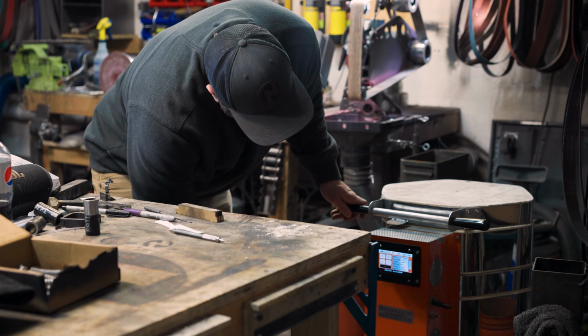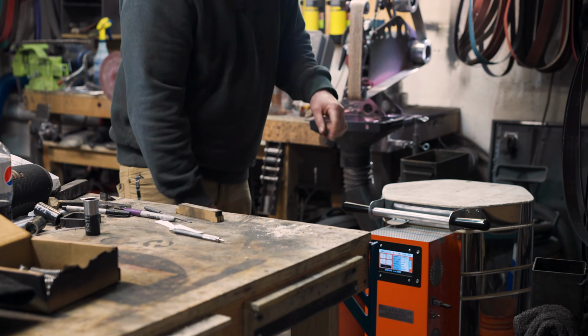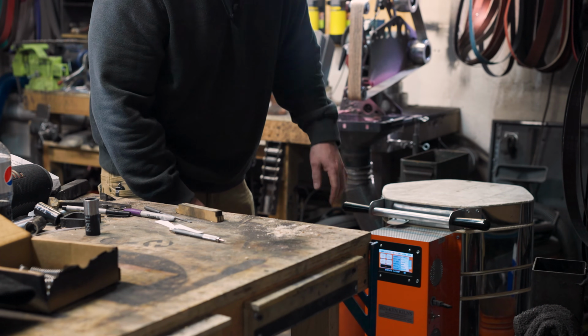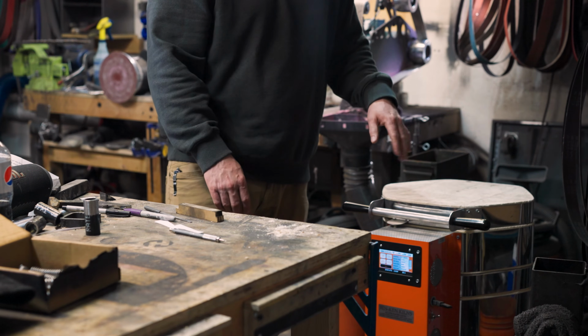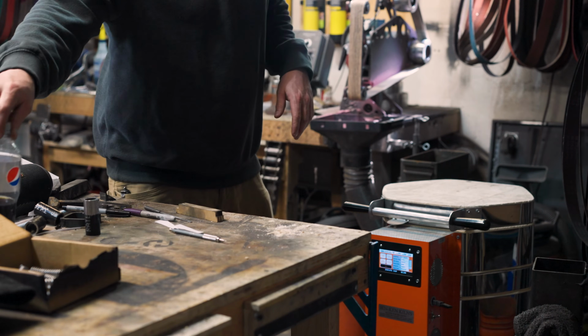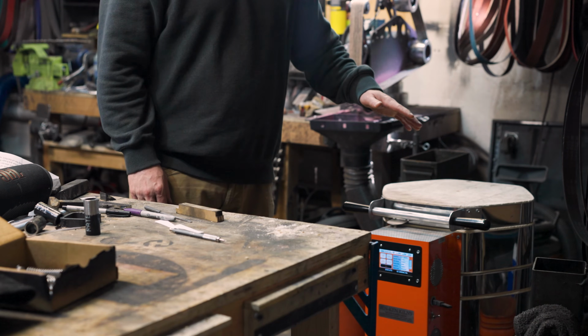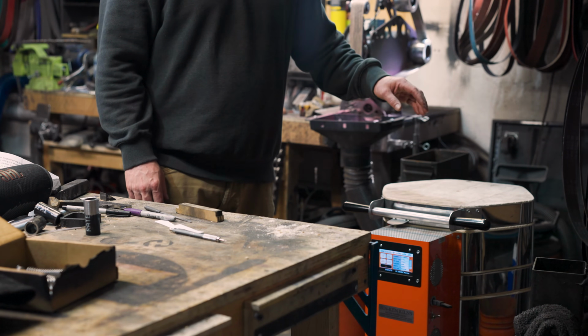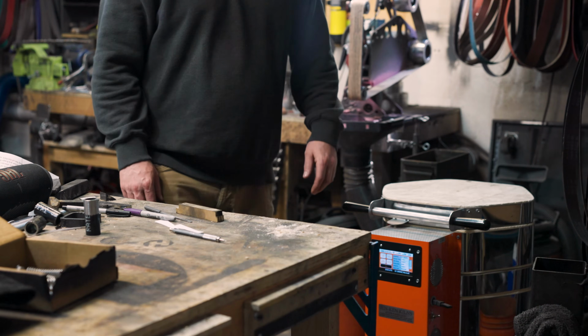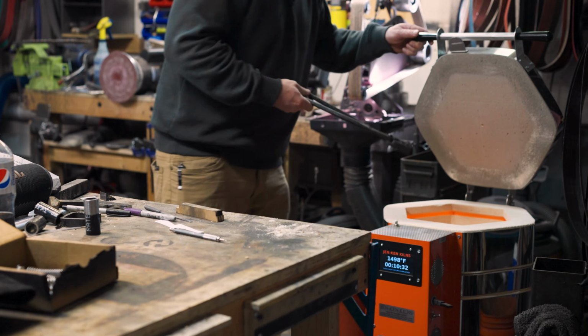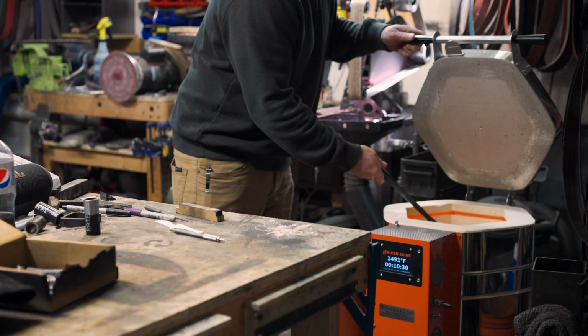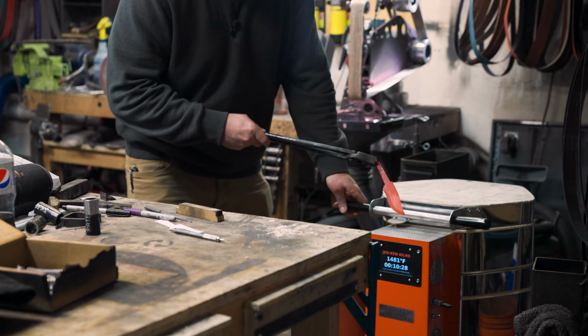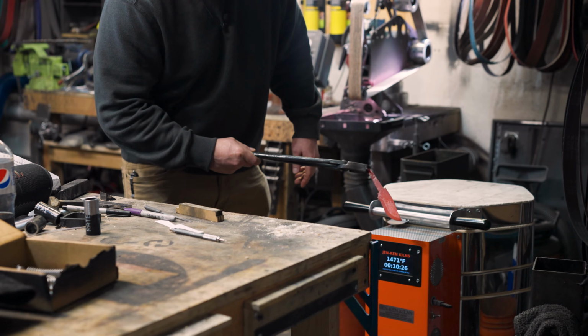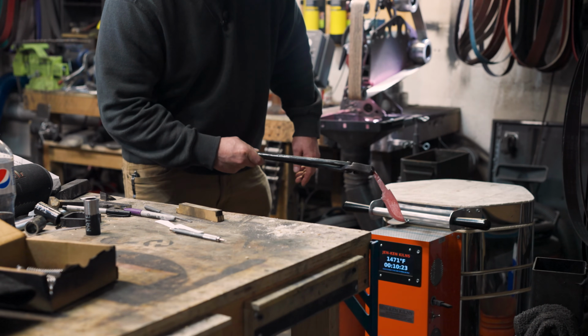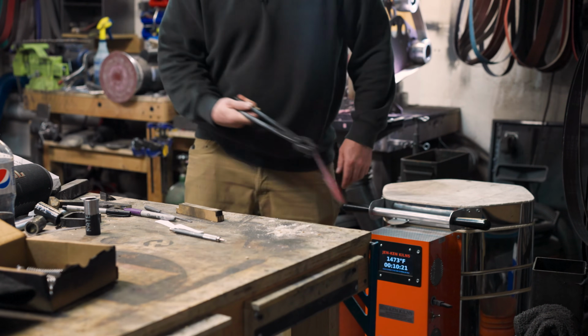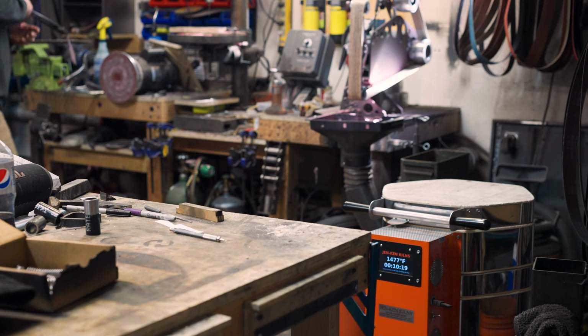Okay, we're up to 1500 on this. I'm going to let this soak for just a few minutes. You don't have to let it soak, but I just tend to like to let it soak just in case, just to make sure that we're heated all the way through the steel. Okay, let's pull this out, let it cool. So you can see nice 1500 degree color, nice dull red. Onto the cooling rack.